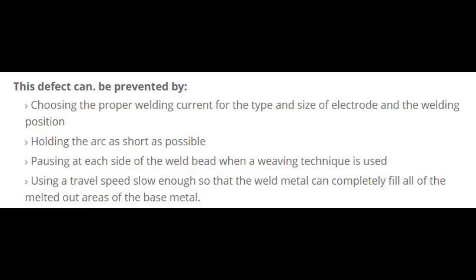This defect can be prevented by: choosing the proper welding current for the type and size of electrode and the welding position, holding the arc as short as possible, pausing at each side of the weld bead when a weaving technique is used, and using a travel speed slow enough so that the weld metal can completely fill all of the melted-out areas of the base metal.